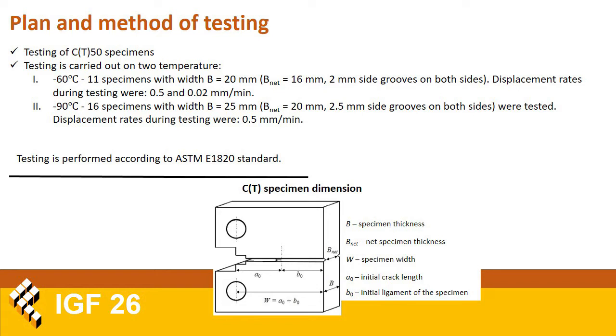The testing of the CT50 specimens made of the previously mentioned steel was carried out at two temperatures, as mentioned before. A total of 11 specimens with B net 16 millimeters and 2 millimeter side grooves on both sides were tested in the first set of testing at minus 60 degrees Celsius. This first set of specimens was tested with displacement rates of 0.5 and 0.02 millimeters per minute.